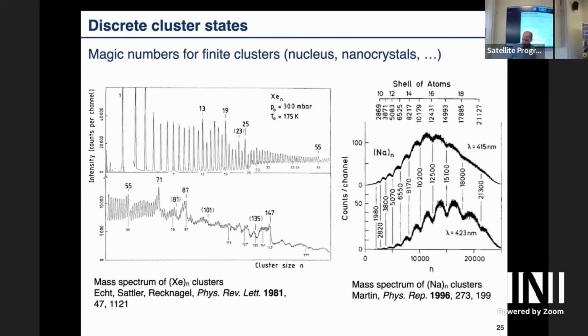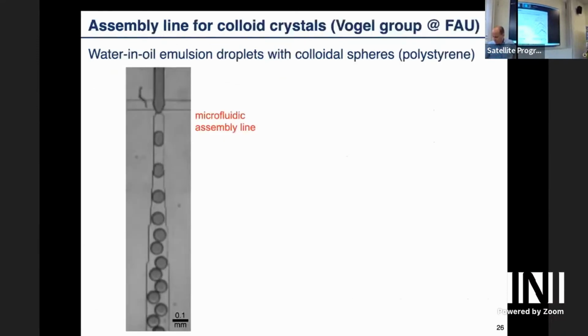And you can even go on. So this is work from the 90s, where they did spectroscopy on sodium clusters, and you go to much larger clusters, 20,000, and you see these oscillations in the frequency of seeing certain sizes, which shows that certain sizes are more stable or more common than other sizes. And again, these are magic number clusters. Whenever you have a maximum, we would call this a magic number. When you have a minimum, it's like a non-magic number cluster. But it's smeared out because of thermodynamics and so on.